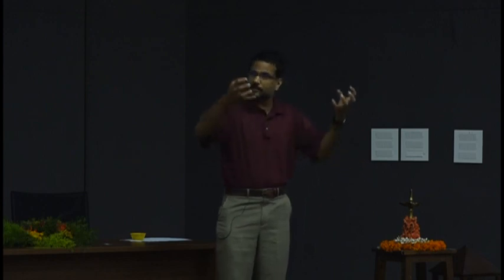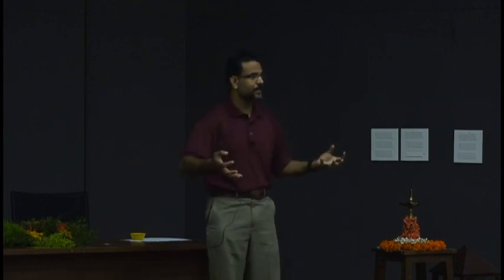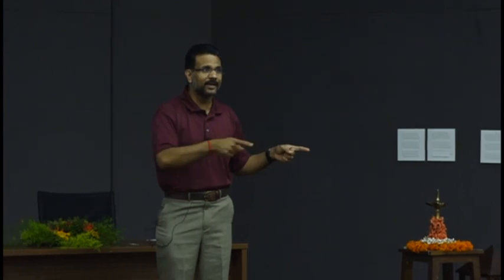So the hydroxide concentration is effectively dropped. Because the hydroxide concentration is effectively dropped, go back to what I said earlier: what is moving around here? Hydroxides. Because the hydroxide concentration was dropped, there are not enough hydroxides to flow, therefore you will get a lower current. Your lower current is because it lowered the hydroxide concentration, not only because silica fume was great.